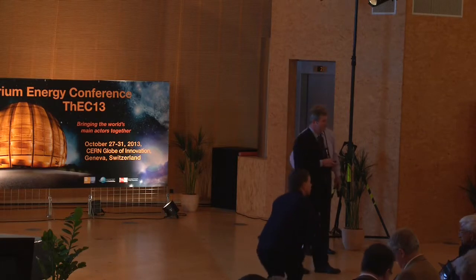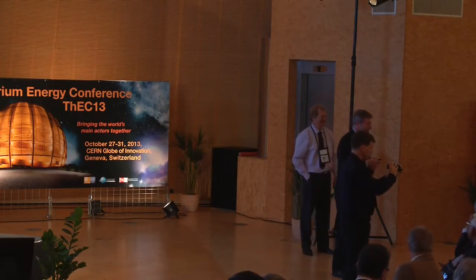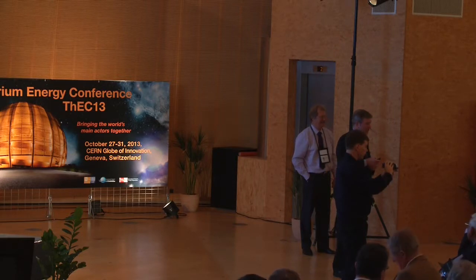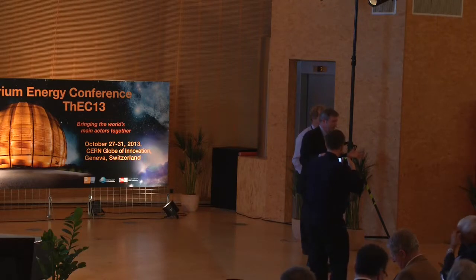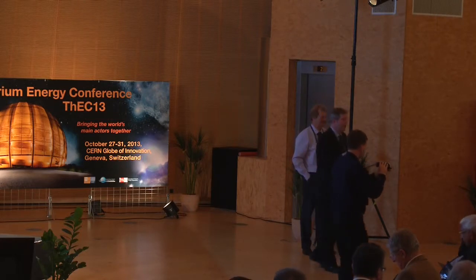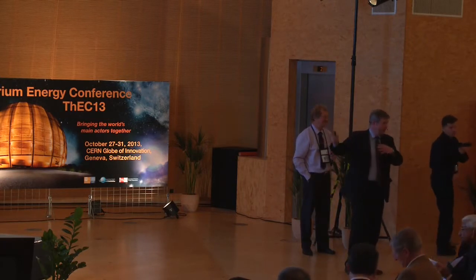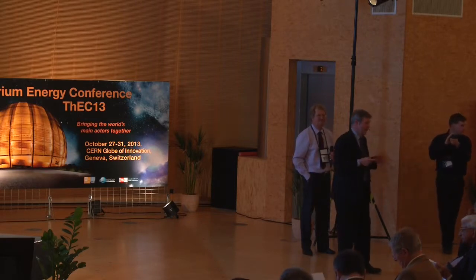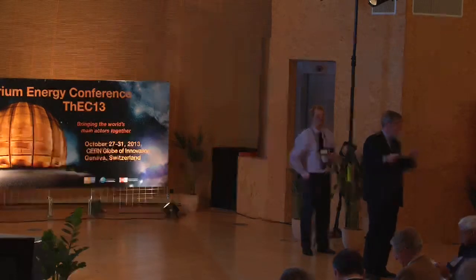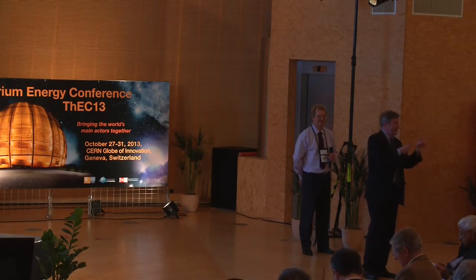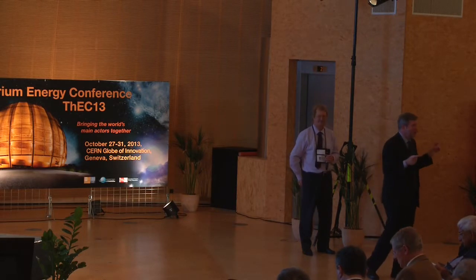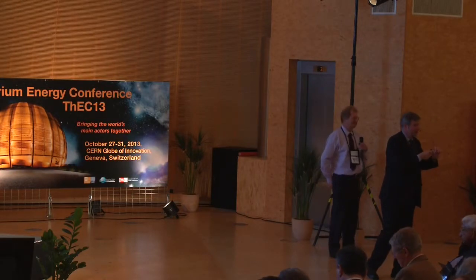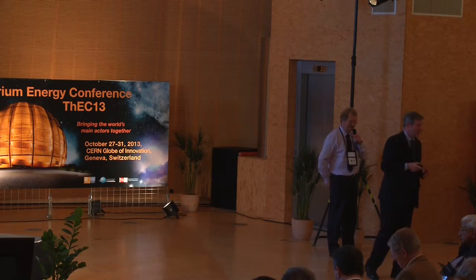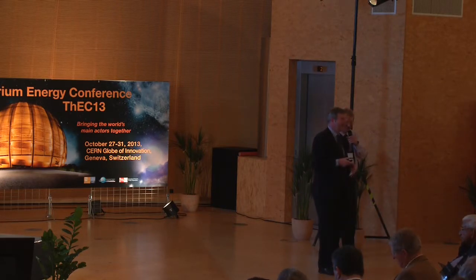Okay. Yeah. I'm going to go in the other direction. Have you considered, or you plan on going in the direction of adding essentially fission product surrogates or interactions with materials for the pressure boundary? Absolutely. So by fission products, you mean, say, minor actinides and so on? All fission products. Oh, yeah, well, so any ionic fission product, indeed, yes. And we've done work on the rare earths in here, and what I would have difficulty doing is doing, say, gaseous product, the rare gases, for example. Again, I'd need a different interaction model. Well, it might work. I might be able to do that, but I'd need a different type of interaction model in order to deal with things like xenon in these molten salt mixtures. But it's an interesting possibility. Okay, that one might work, whereas applying these methods to lithium metal would not work.